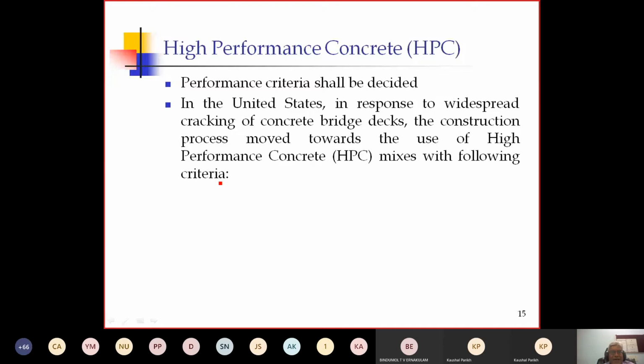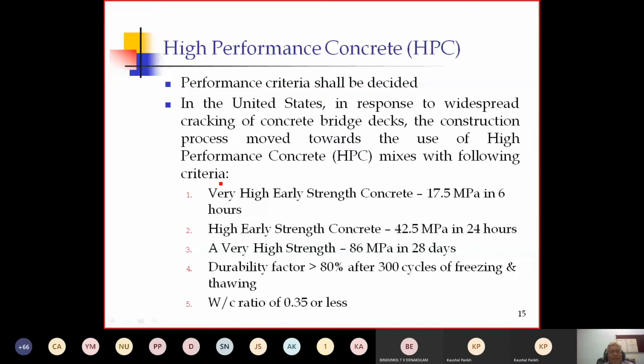Let us see: very high early strength concrete, that is 17.5 megapascal in 6 hours. High early strength concrete, that is 42.5 megapascal in 24 hours. A very high strength, that is 86 megapascal in 28 days. Durability factor should be more than 80% after 300 cycles of freezing and thawing. See, this is the special criteria. The first three criteria are related to the strength, but this fourth criteria is related to durability, that is 80% after 300 cycles of freezing and thawing. Water cement ratio of 0.35 or less.